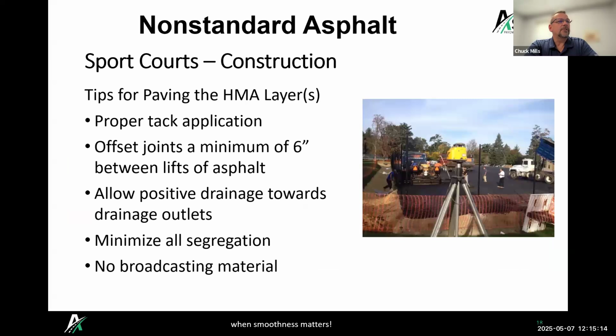Some tips for when we're constructing the asphalt. Obviously, if we're placing it in layers, proper tack application is always important so that those layers act as one. You might want to offset joints in between the layers so that you don't have a plane of weakness all in one spot. You want to allow positive drainage towards any drainage outlets.